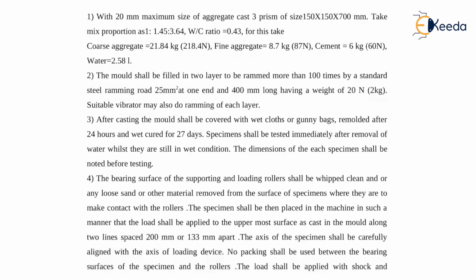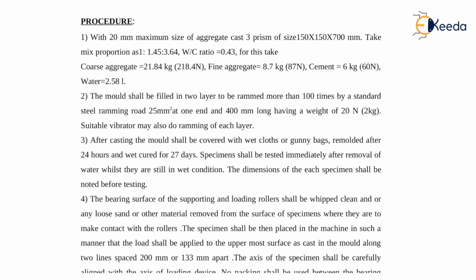Then after casting, the mold shall be covered with a wet cloth or gunny bags, demolded after 24 hours and wet cured for 27 days. The specimen shall be tested immediately after removal from water, while they are still in wet conditions.